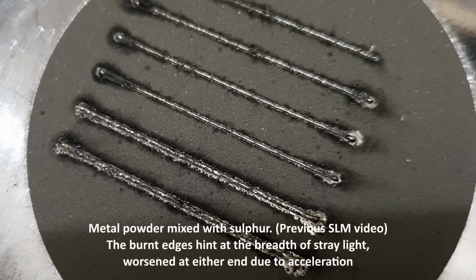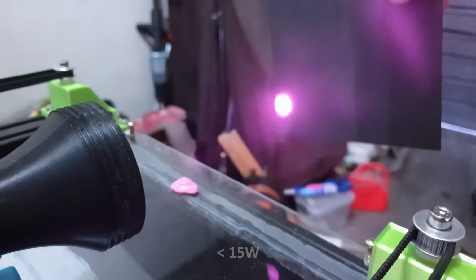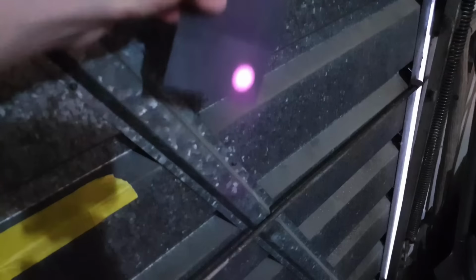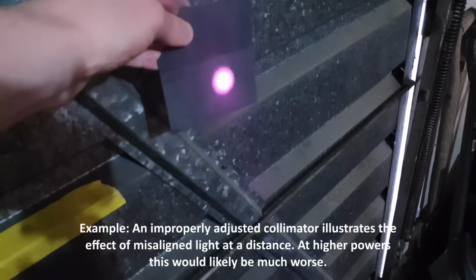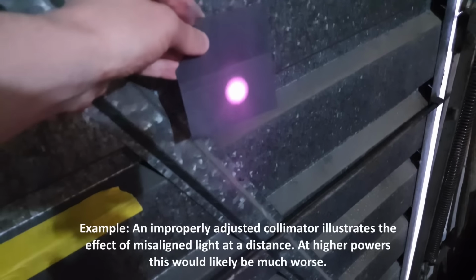I suspect there was a high enough degree of stray light which led to the adjacent powder being heated enough to create the surrounding gas to rapidly expand, blowing the powder away and through the plasma stream. Since the power was significantly higher to adapt to a thicker first layer, this likely worsened the effect, and without the tools to effectively measure the degree of stray light, it totally escaped me. I think denudation still plays a role in this, but to what extent I'm not sure.